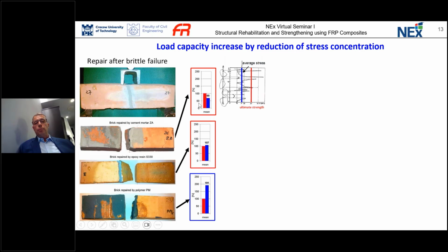If we assume that 100%, this red bar, is the original strength of the brick, and we repair it with cementitious mortar, strong cementitious mortar, we receive a lower ultimate strength. When we apply epoxy resin, high strength epoxy resin, we are able to improve the strength of the weak material by about 7%. When we apply flexible polyurethane, in this case of PM type, you can see that the increase of ultimate strength is almost double, and also the damage is in the form of cohesive failure of the polyurethane.